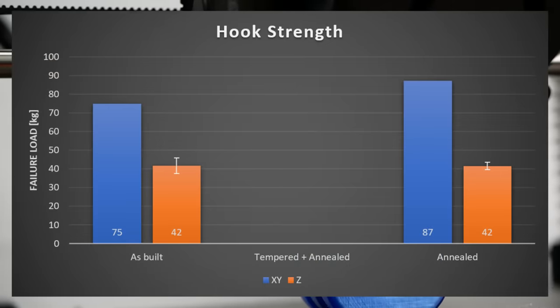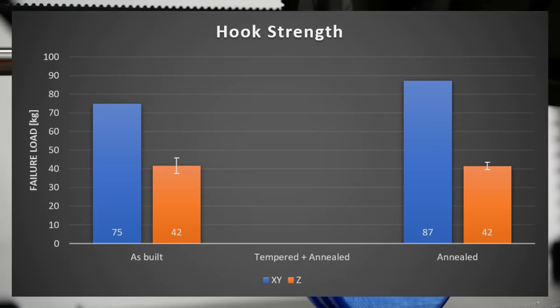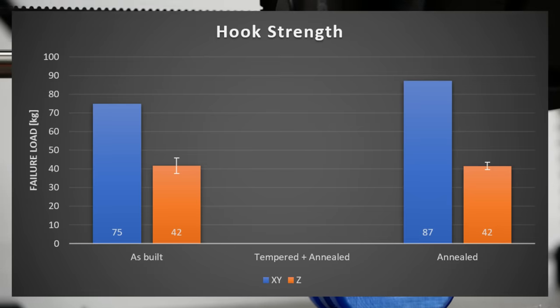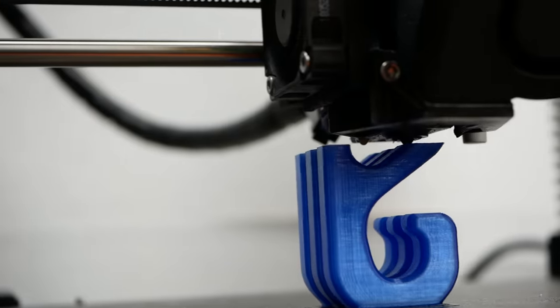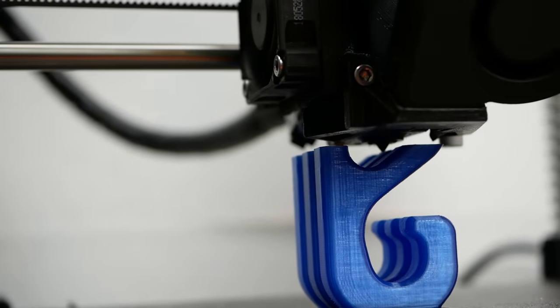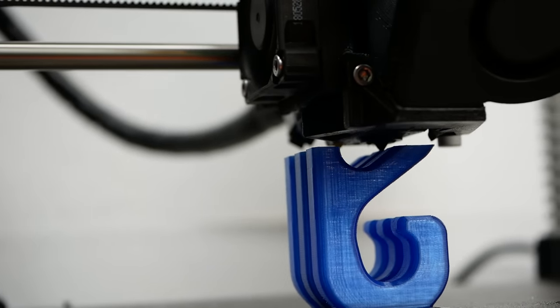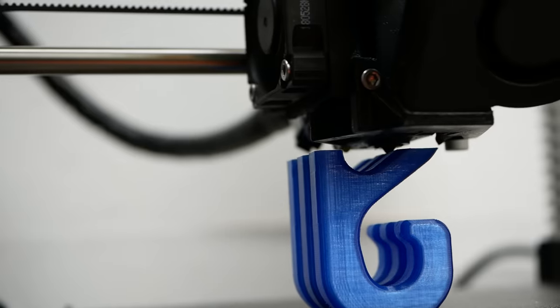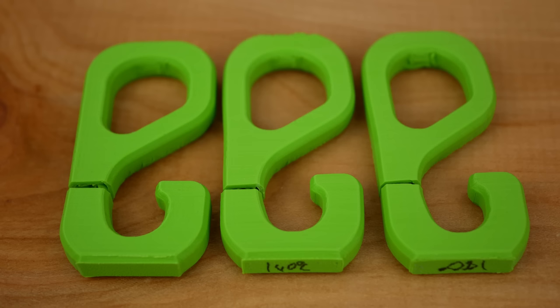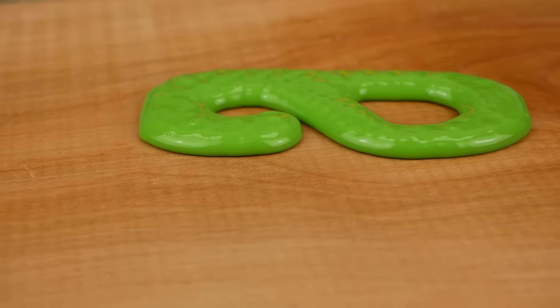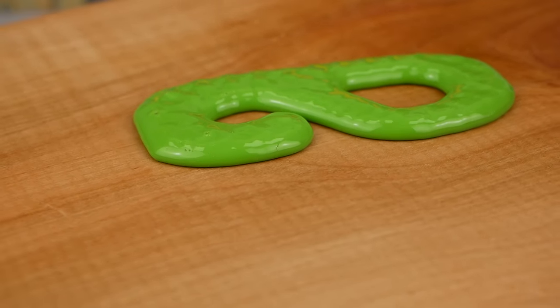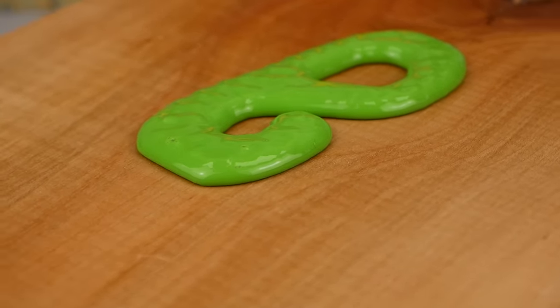So this is quite a bummer but kind of confirms what I already experienced in the past. At least in all of my investigations I was never able to improve layer adhesion with this heat treating process. The layers don't melt together better. And trust me, I tried. In my pre-tests I even tried higher annealing temperatures of 140C and 180C with parts that I submerged in sand. I had to use the sand for the higher temperatures because otherwise my test hooks just melted away directly.